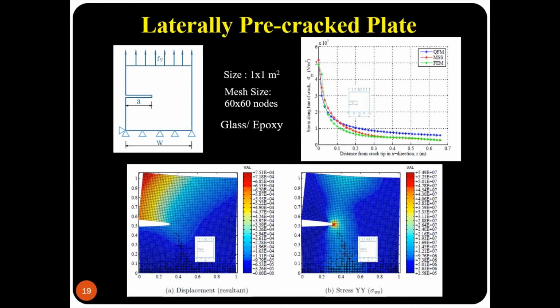So for these simulations, we can see here the full field displacement, and this result is in good agreement with the results present in the literature. Here we can see the full field stress, that is sigma YY, full field stress sigma YY for the laterally pre-cracked plate. And a very important conclusion here is that you can see there is a stress concentration near the crack tip, and from this we can conclude that the MSS model is capable to simulate singularities in front of the crack tips as shown here.